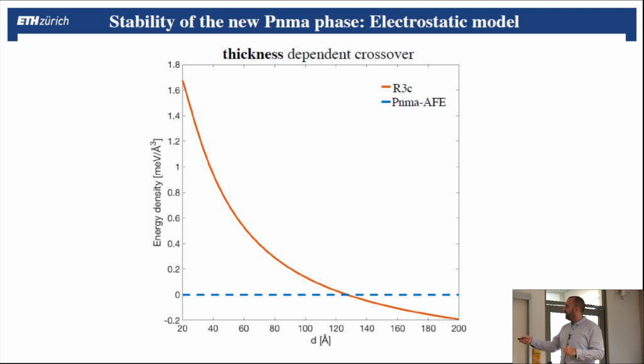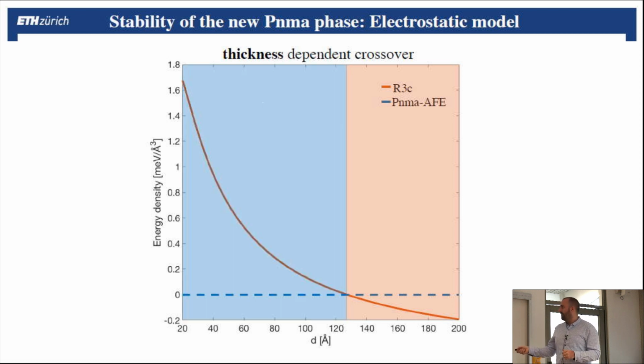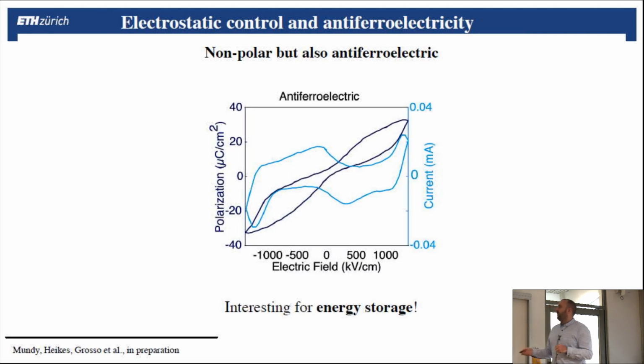And for the polar case, you see that the energy decreases as a function of the thickness, meaning that for large thicknesses, this is more favorable. And this is intuitively correct, because you imagine that if you create a very large system, you will want to recover the bulk behavior, so find again the ground state. But interestingly, at smaller thicknesses, the non-polar case is more favorable than this extra electrostatic cost. And this explains actually why this non-polar phase is observed experimentally.